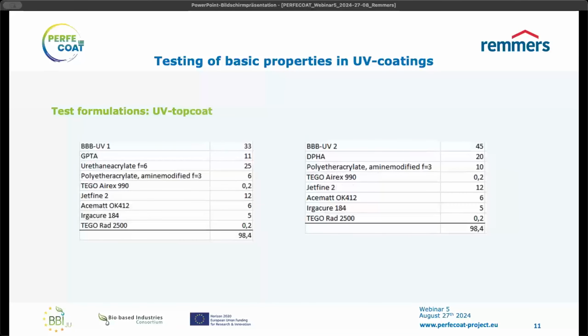Here you see how it's looking for the top coat formulations. Once again, a bit lower content for the bio-based binder number 1, because to achieve sufficient mechanical properties, we had to combine with a bit more of a fossil-based standard resin. In this case, a hexafunctional polyurethane acrylate. But still, with a recipe share of 33%, this means 40% calculated only on the organic part of the formulation.